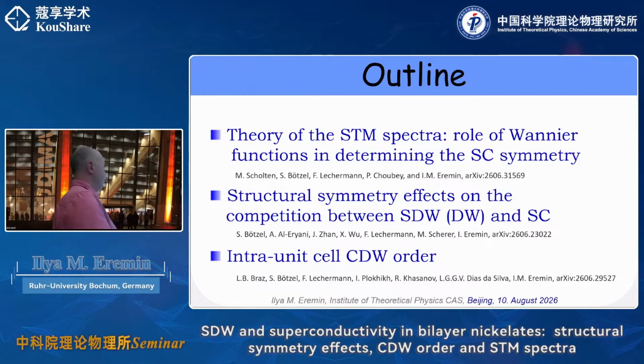Well, in this system, it is known that the system is magnetic when it is in the orthorhombic phase. However, if you look at the fermiology, it looks surprisingly similar to the one we see under pressure, or we expect to see under pressure. So then we ask a question, and this is actually a collaboration with Sishan Wu's group and with June: can we expect that maybe even the orthorhombic material may become superconducting? And we were discussing it using a method that can self-consistently describe magnetism and superconductivity together, so with FRG, functional renormalization group.